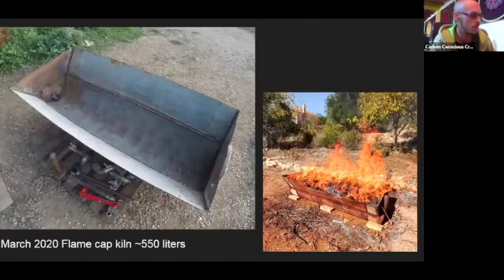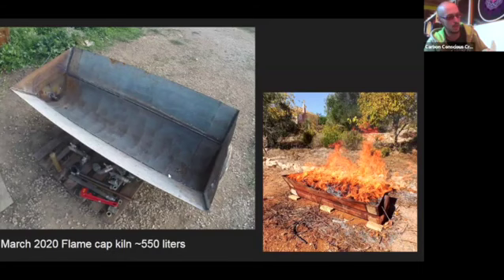And then at a certain point, I had this large hot water tank, a solar hot water tank, and I made a proper flame cap kiln above the ground. And as soon as I used it the first time, my first thought was, why did I not do this much sooner? Because the convenience of having a flame cap kiln above the ground compared to a pit burn is enormous, because you can escape from a lot of the heat. With a pit in the ground, you have all that heat directly in your face. Whereas with a kiln, if you approach it from a bit lower, you're shielded by the sides of the kiln. They're much more convenient to use.